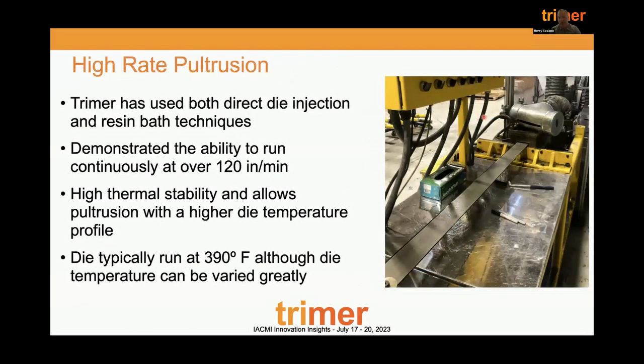One of our biggest application spaces right now is pultrusion. If you're familiar with pultrusion of fire-resistant composites, you're typically looking at brominated vinyl esters, which are being outlawed in the EU at the end of the year. Or you're thinking about phenolics. Phenolics have a poor toxicity profile, very high void content due to condensation reaction, and poor mechanical properties as well. We're able to run very quickly. We've demonstrated up to 120 inches per minute in certain profiles, and we can generate all of those mechanical properties and the fire resistance that's required for these parts from tooling in a high-rate pultrusion.